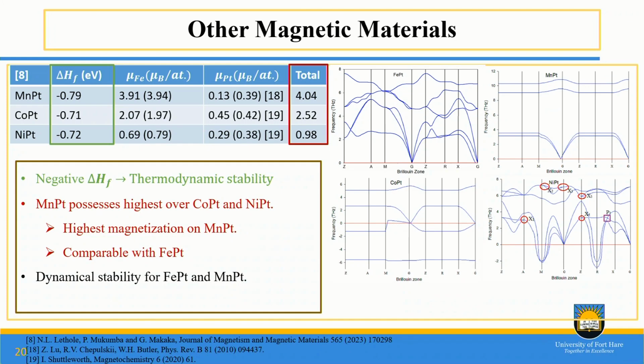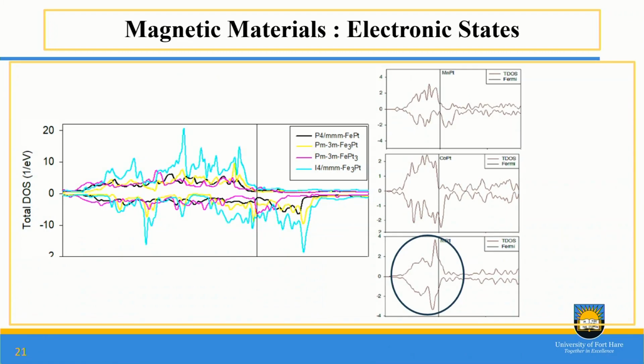We have also done other compositions, with manganese, cobalt, and also nickel. This study is not as advanced as the one on iron and platinum, but we have seen that they also give us good magnetic moments, especially manganese platinum, which is very much comparable to iron platinum. They also give us negative enthalpies of formation, which shows that everything is stable. We have also calculated the electronic structure to confirm what we have found magnetically.